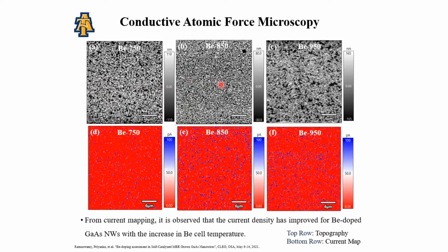The top row shows the topography of an array of vertically aligned beryllium-doped gallium arsenide nanowires, while the bottom row shows the corresponding current mapping of the doped nanowires. From the current mapping, it is observed that the current density has improved for beryllium-doped gallium arsenide nanowires with the increase in beryllium cell temperature.